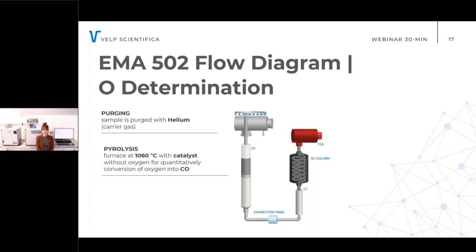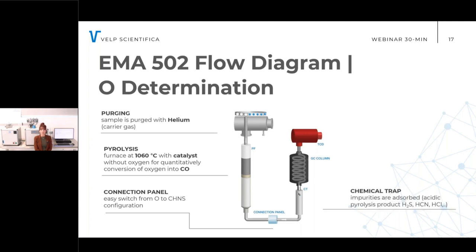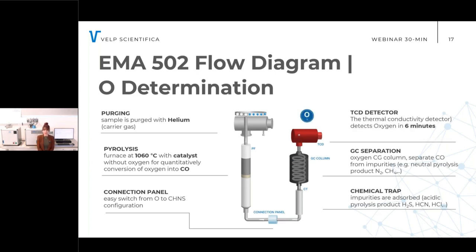During the pyrolysis, the oxygen of the sample is quantitatively converted into gaseous CO. Then, through the connection panel that we have already changed from the CHN of the CHNS configuration to the O, we go through the chemical trap where impurities are absorbed, and then the gas chromatography separation, where the CO is separated from impurities. And after that, of course, the thermal conductivity detector detects the oxygen in just 6 minutes.